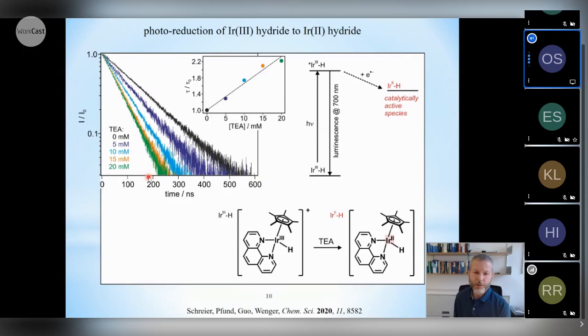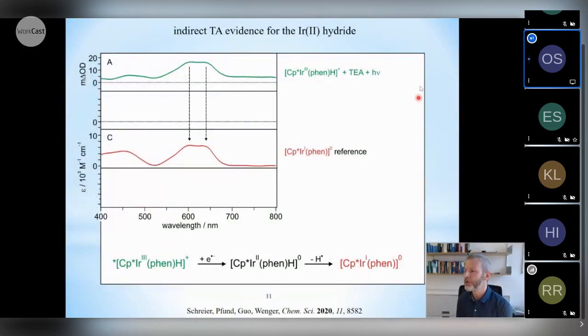And as we titrate in more and more triethylamine, we see quenching, presumably reductive excited state quenching, of this MLCT state, leading us to this hypothetical iridium-2 hydride species, which we believe to be the catalytically active compound. And so we tried to detect this by transient UV-Vis absorption spectroscopy and failed. You see here what happens when we have the iridium-3 hydride in presence of triethylamine.